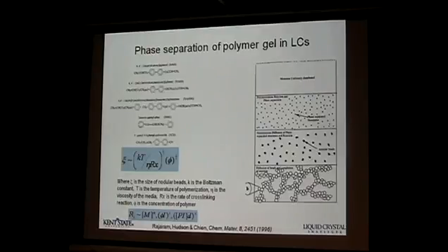Okay, so in general, as I said earlier, we put in less than 10%, maybe few percent into the host, and you form a uniform mixture like that. And then you use some methods to induce the phase separation. There are multiple ways to induce phase separation, using the light, using the energy, and then they start to nucleate. You see, they nucleate at some defect areas.